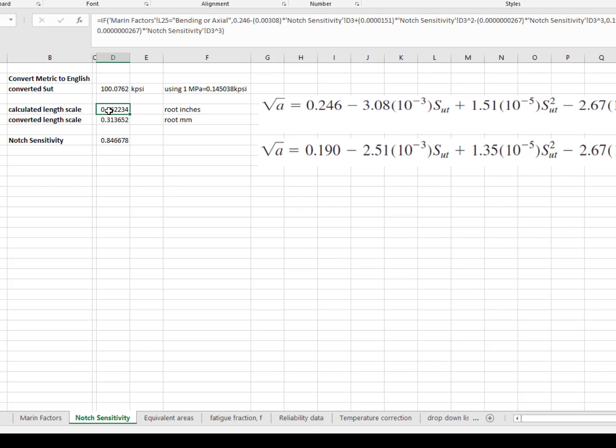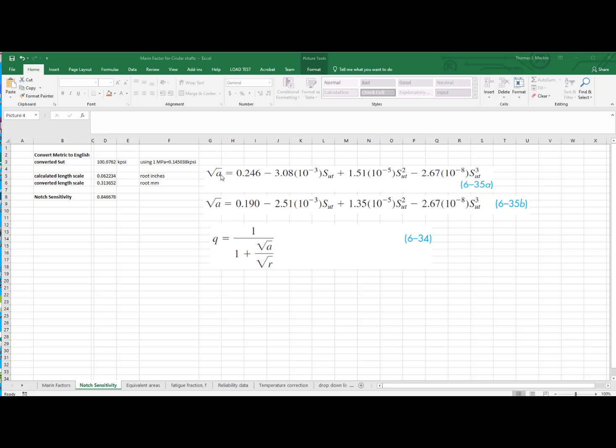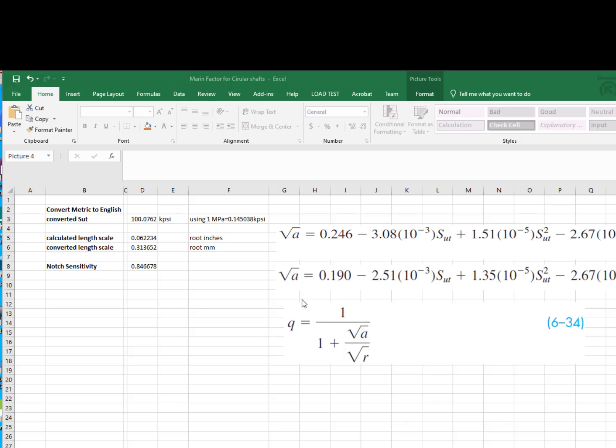This gives me a calculated length scale in square root of inches. Call it root inches here, but I also convert that to root millimeters so that I could then calculate the notch sensitivity using the Neuber equation. So once I have my Neuber length root A, I need my notch root radius so that I can take the square root of it and use equation 634 to calculate my notch sensitivity. And that would go into this cell D8 right here. So I'm going to use equation 634 to calculate D8.